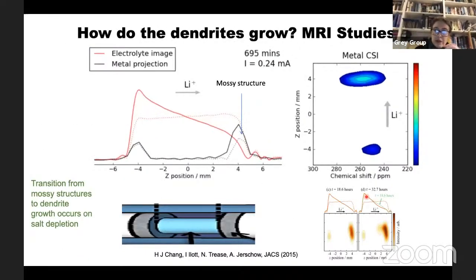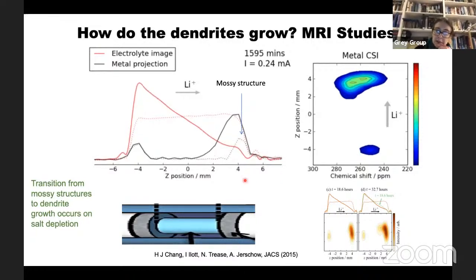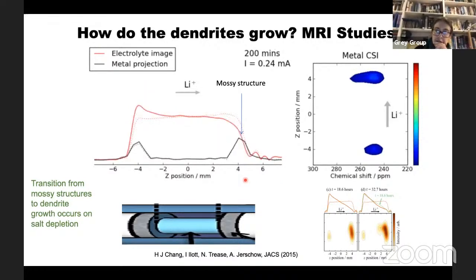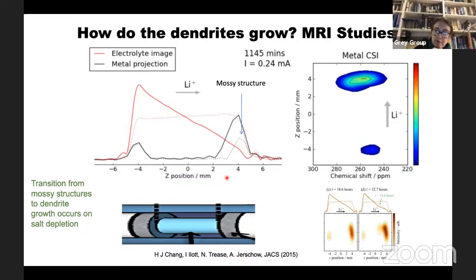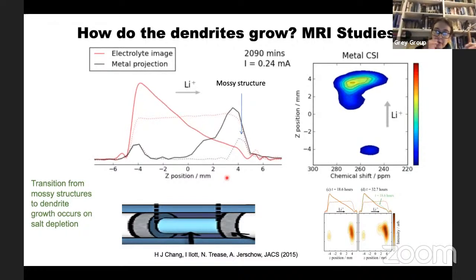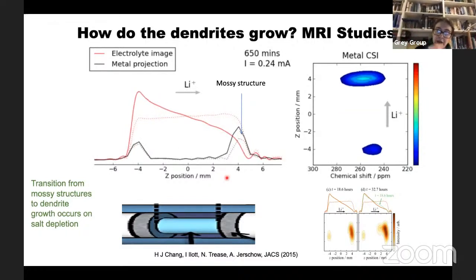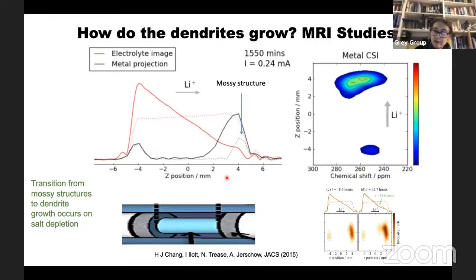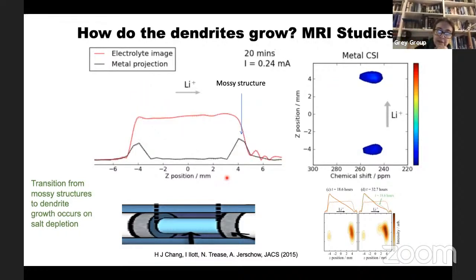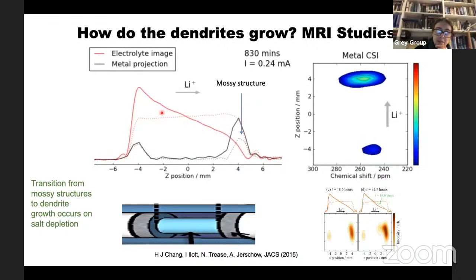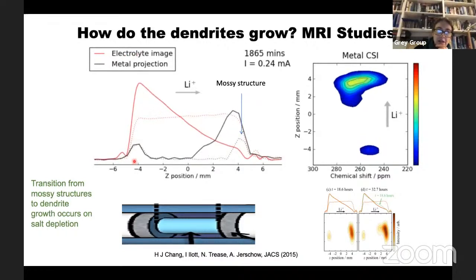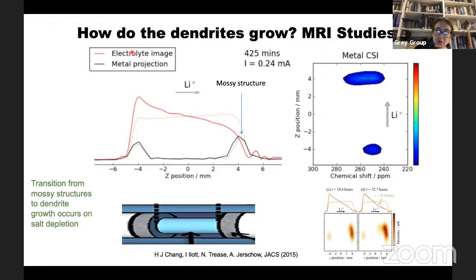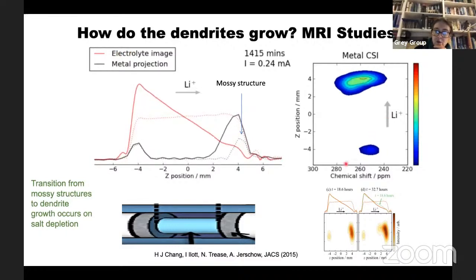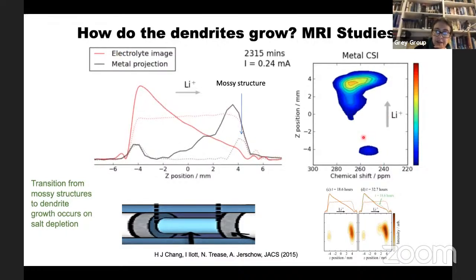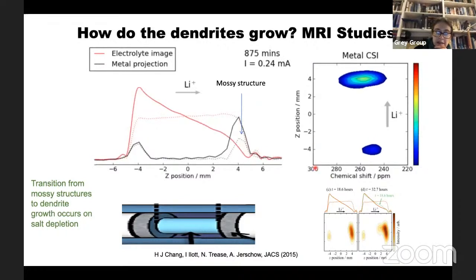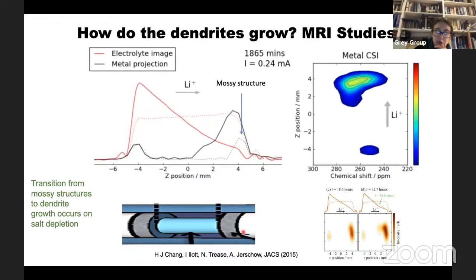Okay, so why do dendrites grow? In order to look at that question, we use magnetic resonance imaging. And the nice thing about magnetic resonance imaging is you can do so-called chemical shift imaging, which is used in functional MRI in the medical field, where you can look at specific frequencies. So this is an example of the electrolyte and the metal. The electrolyte's in red, and on the right is a chemical shift image where you've got the shift versus distance.